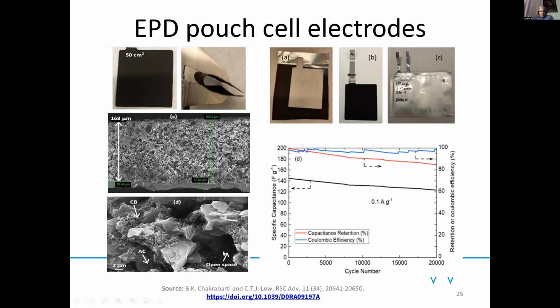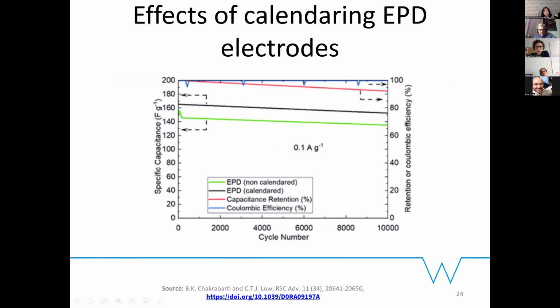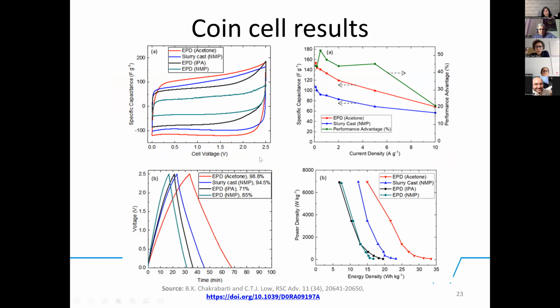usage within the capacitance. One thing I forgot to mention is that the electrolyte we were using was organic, so it's acetonitrile using tetraethyl ammonium tetrafluoroborate salt for all these studies. That's the reason why, if I go back to one of these slides, you can see that the voltage range is quite high, from 0 to 2.5, and it's not limited by the water potential window.